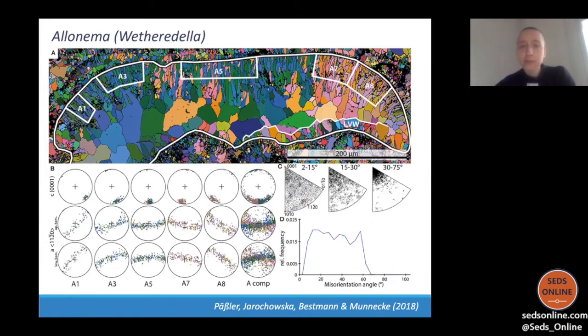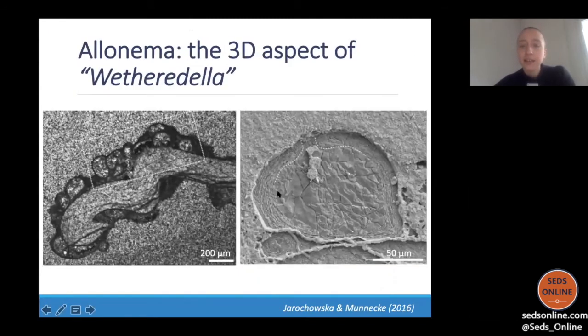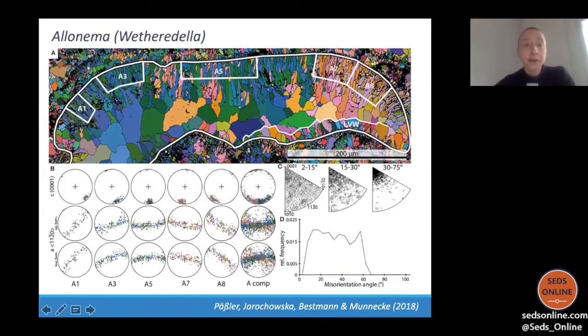So if you want to have a look back at the previous slide, if you look at the edge section, you would think that the crystals are arranged parallel to the surface of the shell. And we find this very often, that etching is misleading. It doesn't really show the crystallographic orientation, or sometimes the crystallographic orientation will be the opposite of what is visible in an etched section. This is the case here, because the grains are actually perpendicular to the surface of the shell. And we'll see this very often.